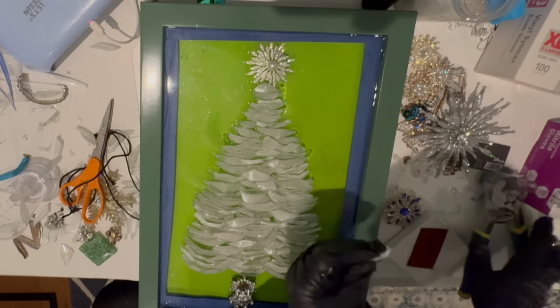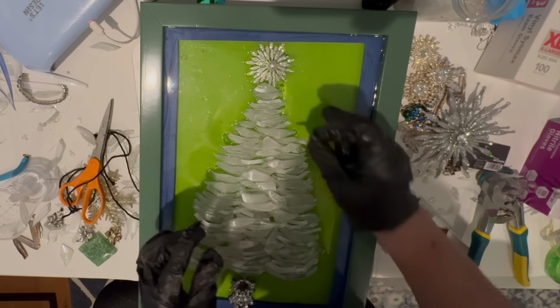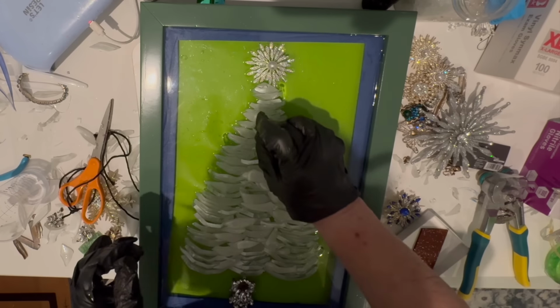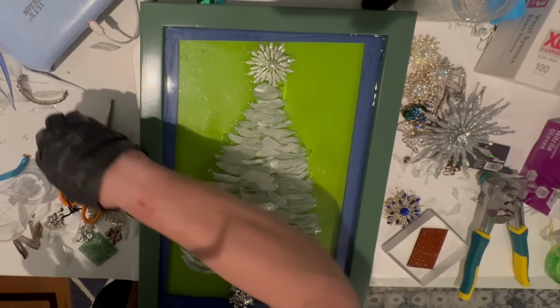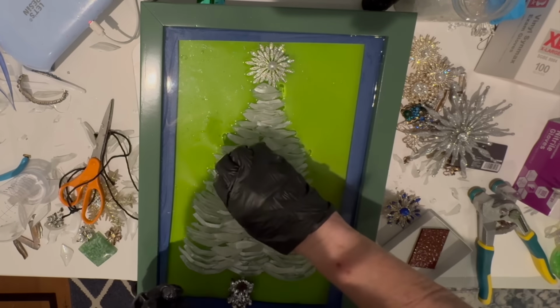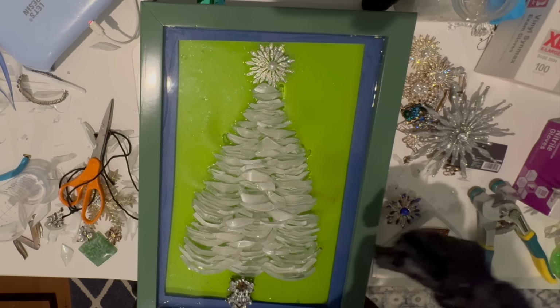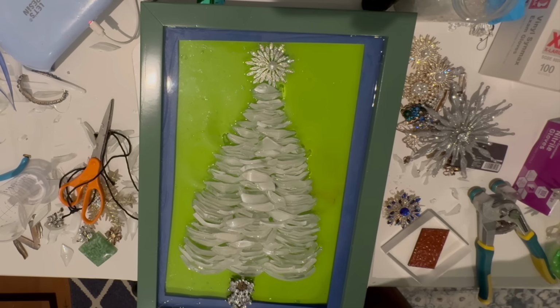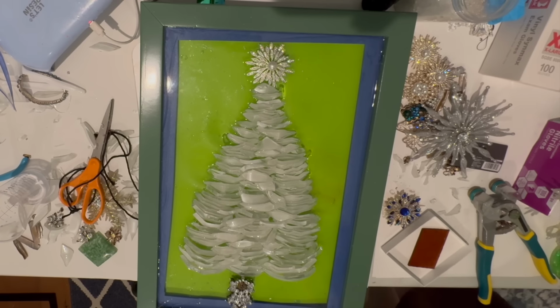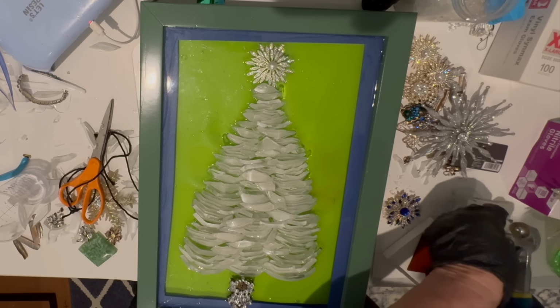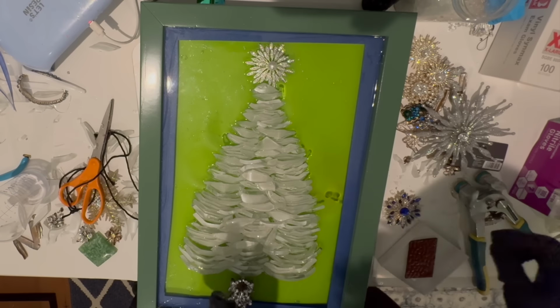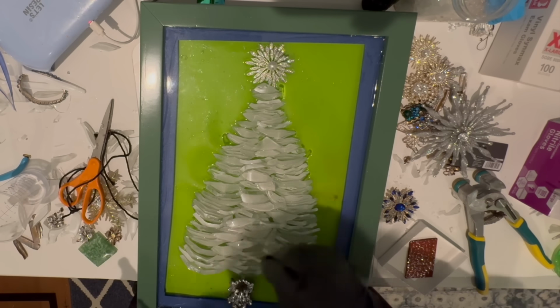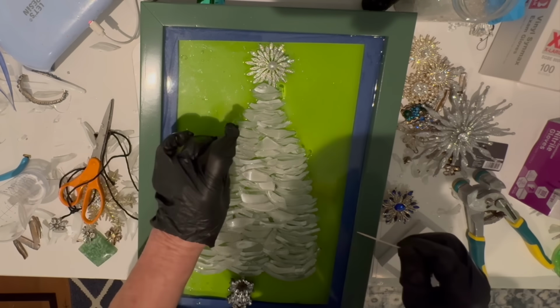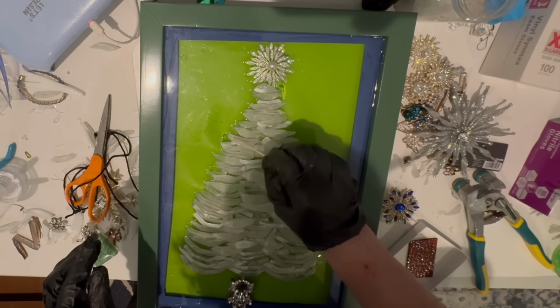This resin actually has a work time of 30 minutes. Its initial cure time is 8 to 10 hours. And final cure time is 24 to 48 hours. It has no VOCs. You can pour it to 1/8 inch at a time, and it cures best at temperatures between 70 and 80 degrees Fahrenheit. I found it very easy to work with.